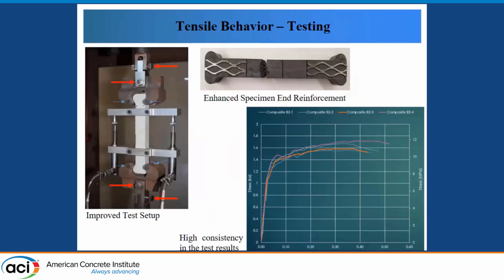For the direct tensile testing, dog bone shaped specimens were used with embedded mesh reinforcement at both the ends to make sure that the specimen failed at the middle. Here, the embedded end reinforcement has been placed on the fractured specimen to illustrate the location of the mesh. The test setup has been significantly improved to provide rotational freedom to the specimen, pointed by the red arrow on the top and bottom, as well as we are able to get reliable deformation measurement. As a result, the displayed test results show very high consistency and quality, which is usually challenging to obtain.